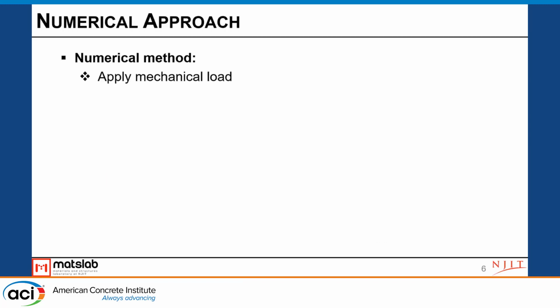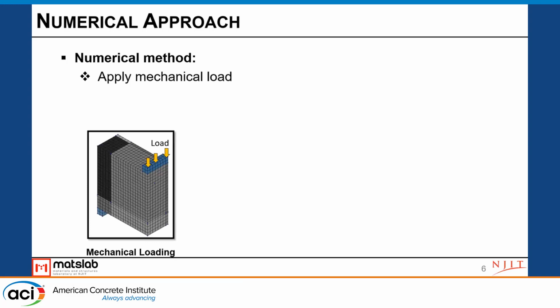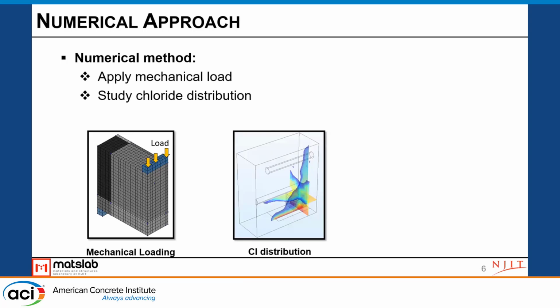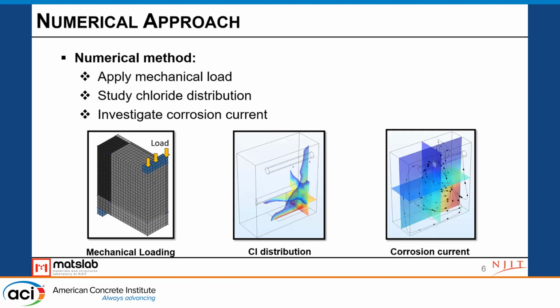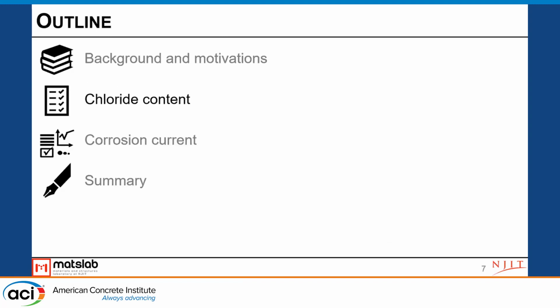With the numerical method, first we're going to replicate what we did in the test. So we're going to apply mechanical load so we can get the cracking information, and then apply this cracking information to conduct the next step study, which is to get the chloride distribution in the cracked specimens. After that, we can define the active corroding area, so we can continue the analysis and get the corrosion current.